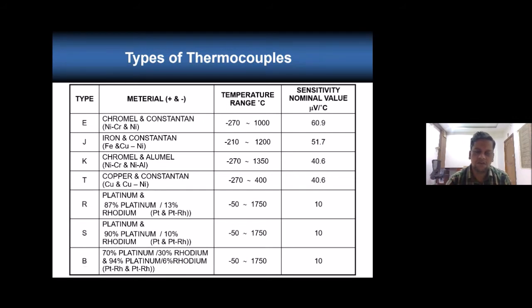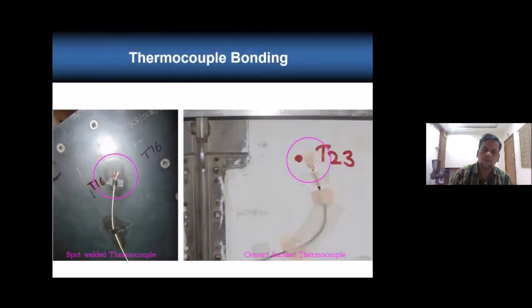These are the various types of thermocouples available. Majorly we use T-type, K-type, R-type, and B-type thermocouples, and C-type also we use. Here it is not listed. C-type mainly consists of two metals, one is tungsten, the other one is rhenium. So that ranges up to a maximum of 2300 degrees centigrade that we can measure, but it needs an inert atmosphere to go beyond 1800 degrees.